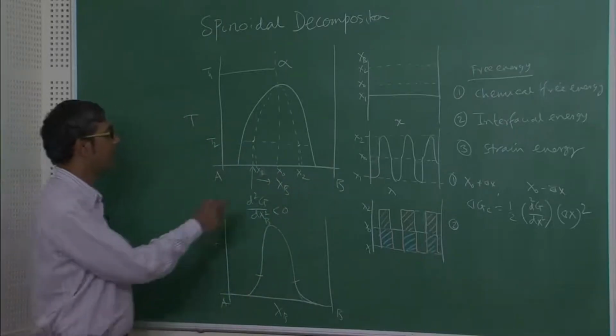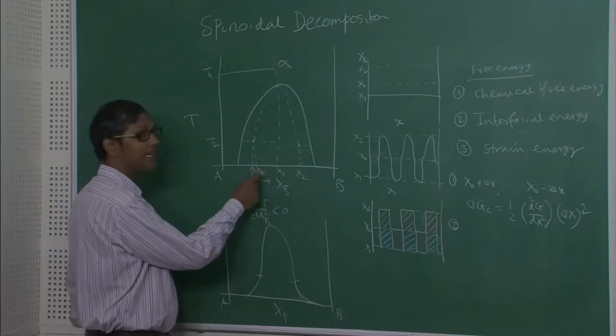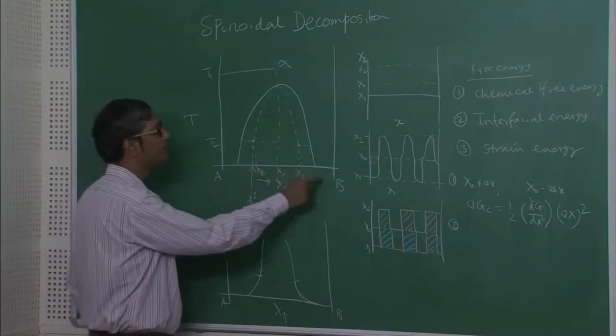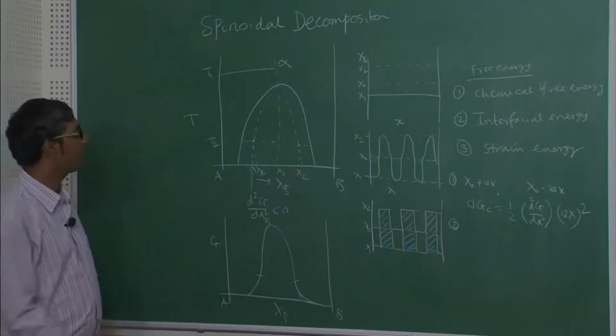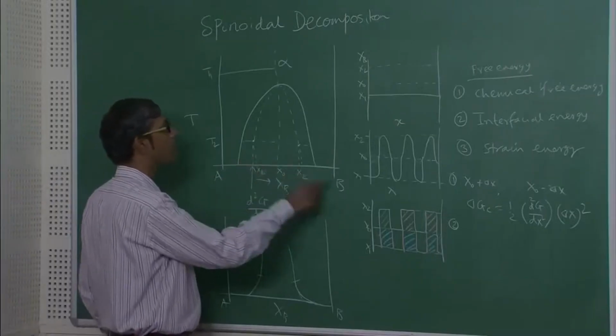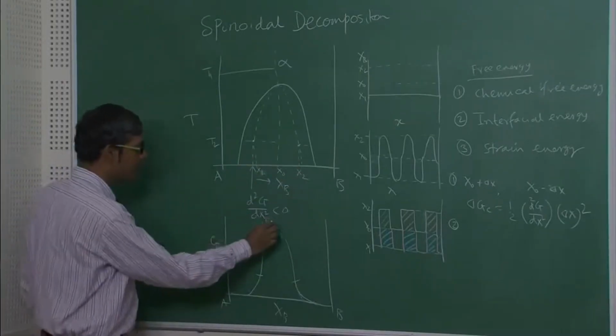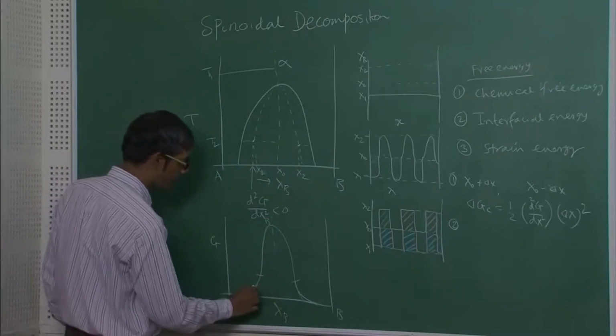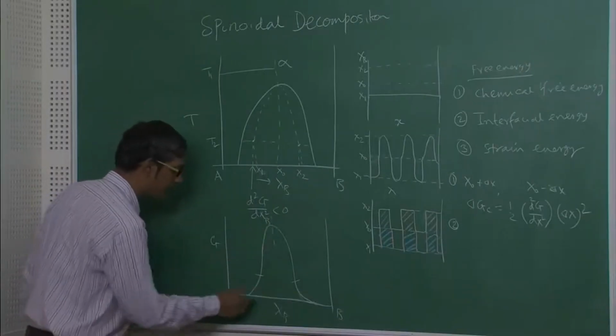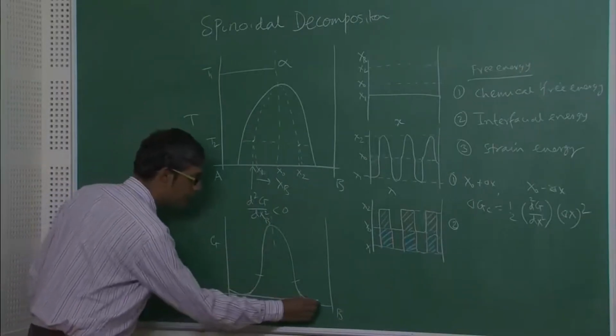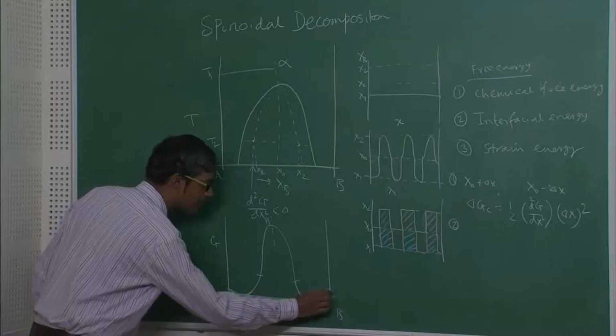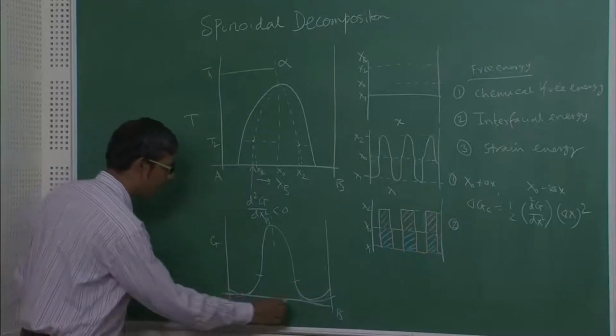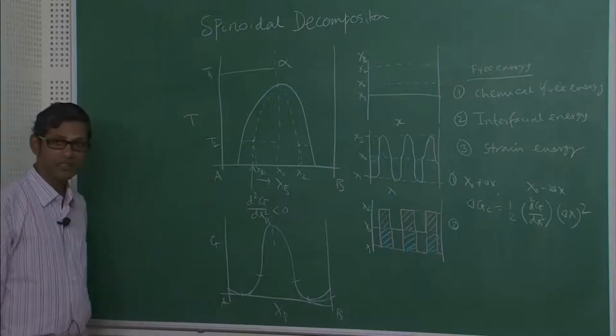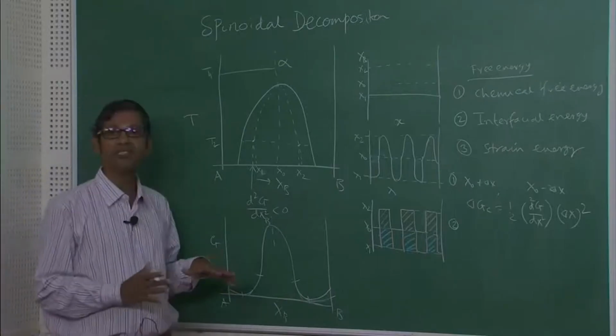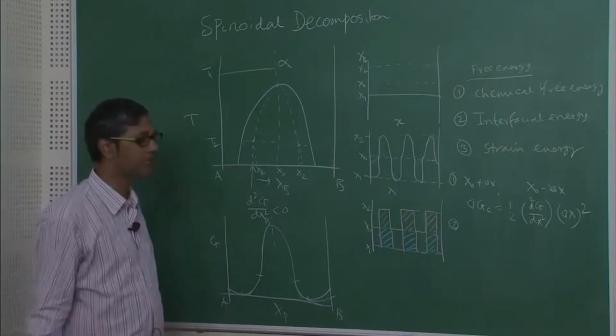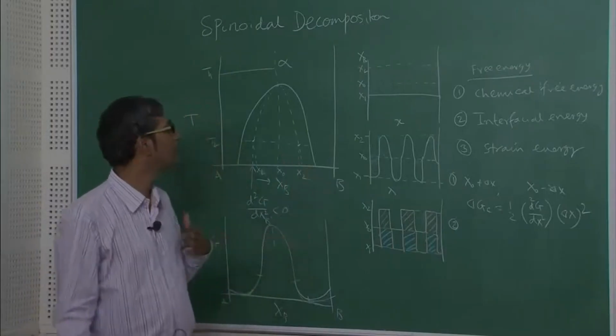So, that means the regions which are A rich have more A clusters, regions which are B rich have more B clusters. As time goes on, this decomposition will happen more and more, as you clearly see, and finally the regions will be A rich and B rich, okay. As you know, this energy curve will look like this, okay, regions will be A rich and B rich. So, this system is basically cluster type, that means you have regions of A clusters, regions of B clusters, that is what spinodal decomposition looks like.